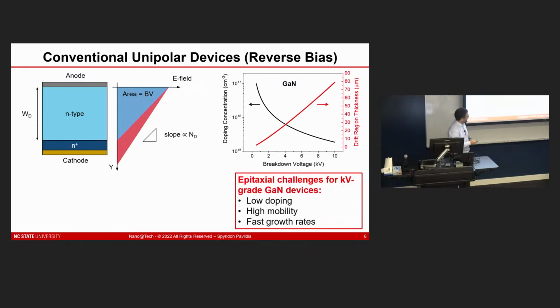So we want to be able to achieve low doping. We want to also have low doping in combination with high mobility. If you have a lot of impurities that you're either purposely or unintentionally using as compensators, those will ultimately also lead to a hit in your mobility and therefore your losses. And if you can, you need to think about ways to do this with high growth rates. But this is sort of the challenge that everyone is dealing with when you try to make a unipolar device.